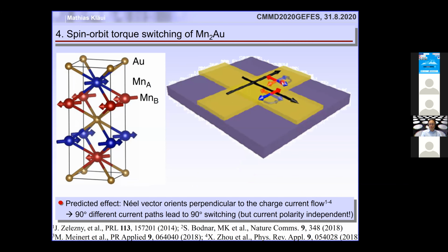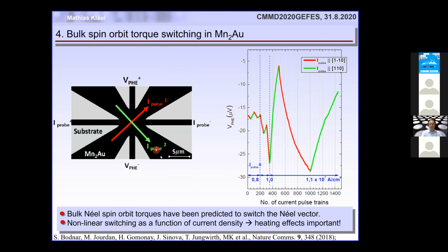And so this we tried out. And it turns out that indeed, if we inject a current along this green direction, which is a 110 direction, or the red direction, which is a 11-bar-0 direction, then we see there is a change in the planar Hall effect, or the AMR. And we see that always the red pulses reduce the signal, the green pulses increase the signal. And when we increase the current density, also the amplitude goes up. So this was published in this paper showing that there are indeed these systems where we can inject currents and actually electrically switch the Néel vector direction. Now, one big problem with these types of systems is that they only work for these crystals which have this inversion symmetry breaking where the two sublattices are inequivalent.